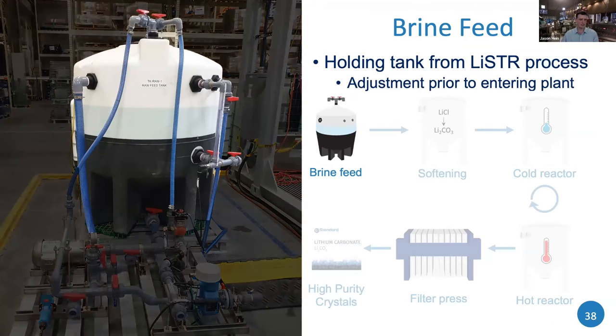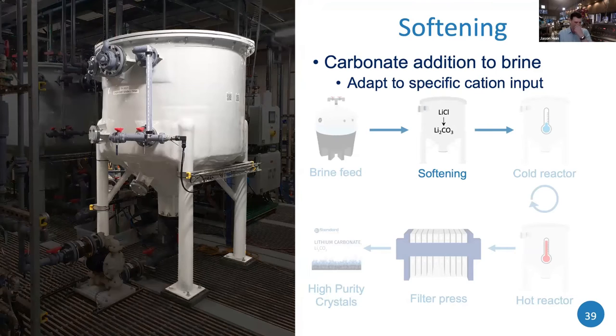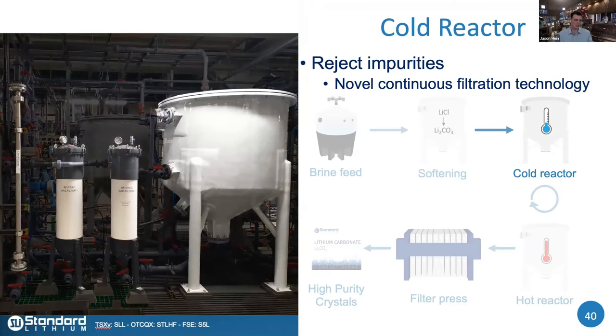So just generally speaking, what we've done now is the different stages, just to show you the thing is live. We have our initial brine material. The softening tank itself is this skid where we carry through our carbonation. We have the technology built into it. We can actually measure what the lithium concentration is, so we can do the carbonation as a response to what's coming into the feed. We have our crystallization reactors where we're using this in-situ bag filtration, but also a ceramic membrane, which gives us our separation on the cold side.